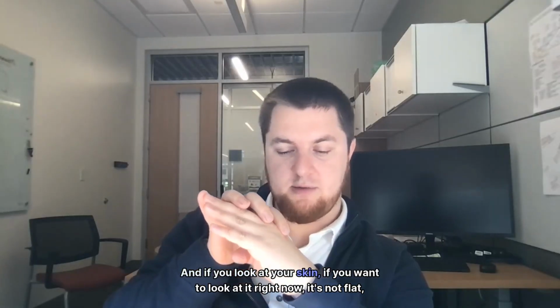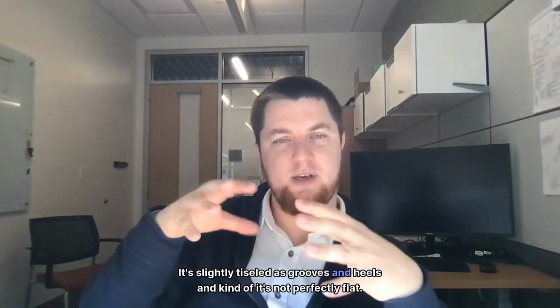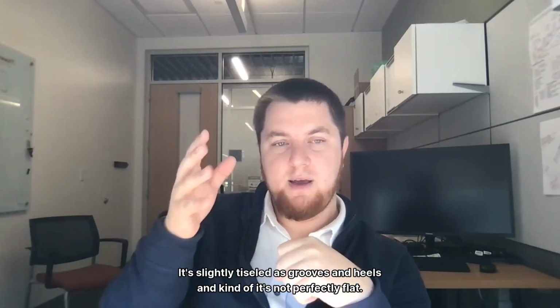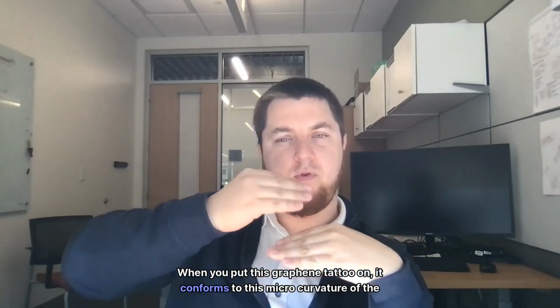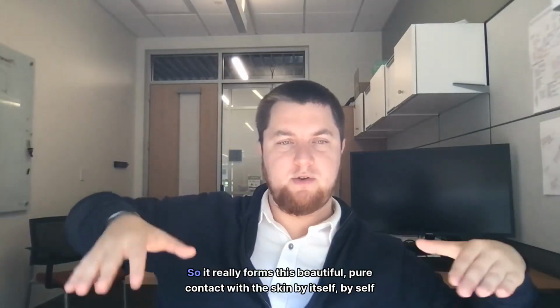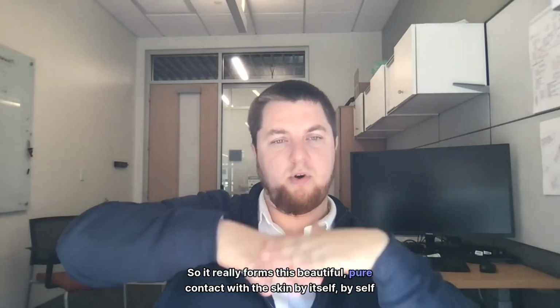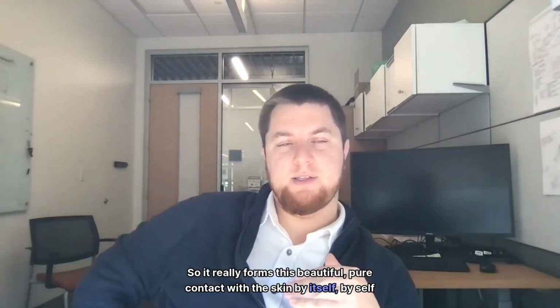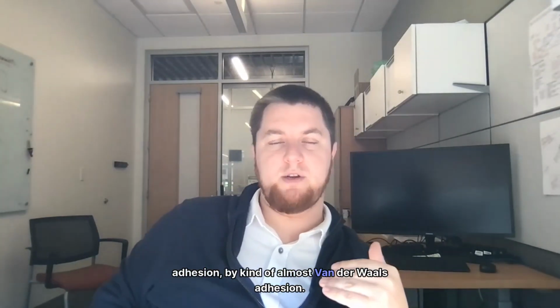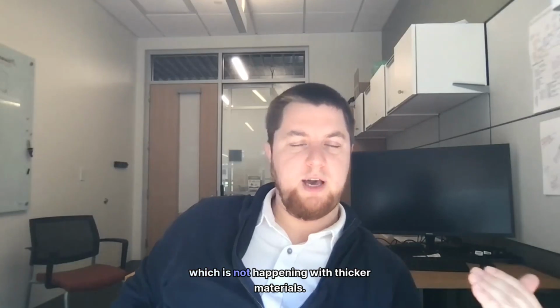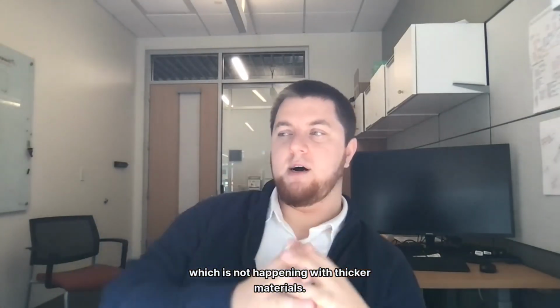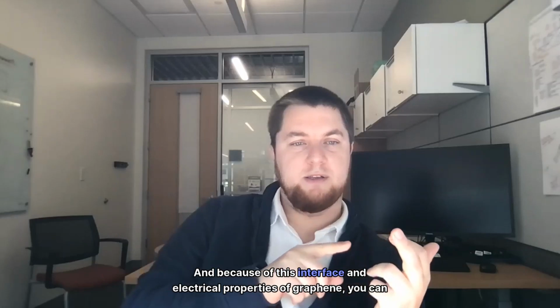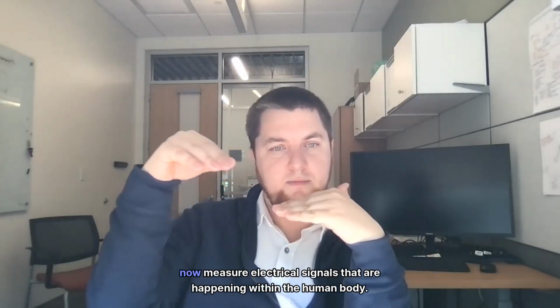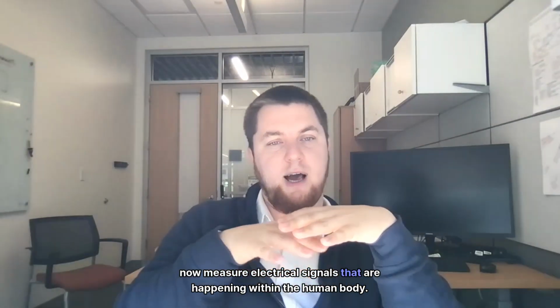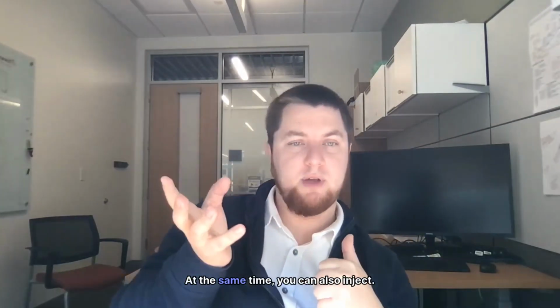And if you look at your skin, if you want to look at it right now, it's not flat, right? It has all these grooves and hills, it's not perfectly flat. When you put this graphene tattoo on, it conforms to this micro curvature of the skin. So it really forms this beautiful, pure contact with the skin by itself, by self-adhesion, by almost van der Waals adhesion, which is not happening with thicker materials. And because of this interface and electrical properties of graphene, you can now measure electrical signals that are happening within the human body. At the same time, you can also inject.